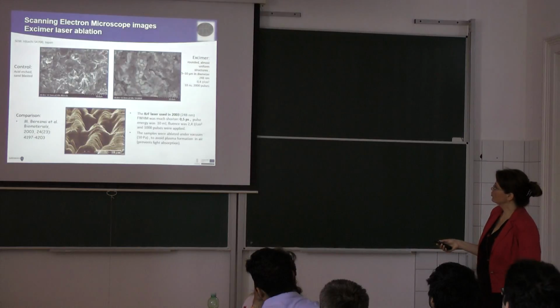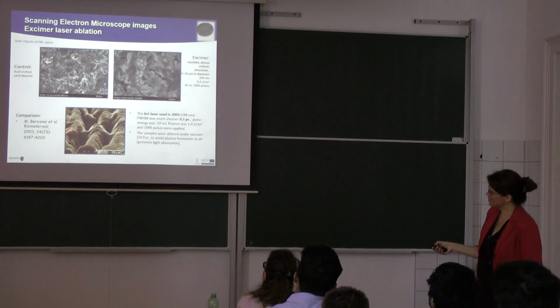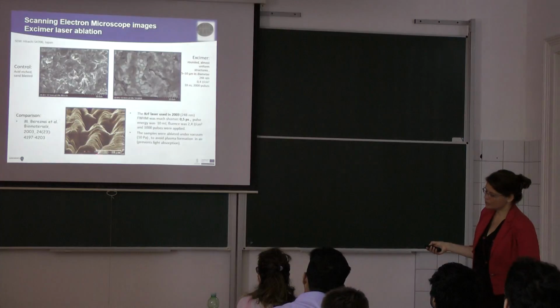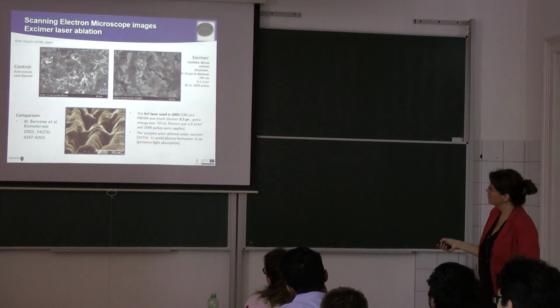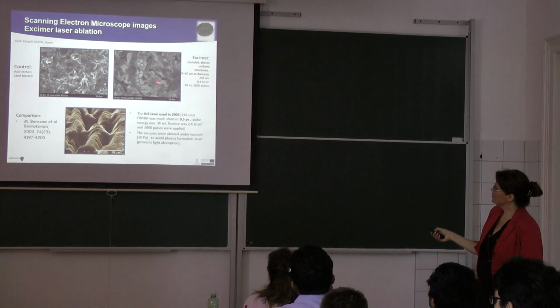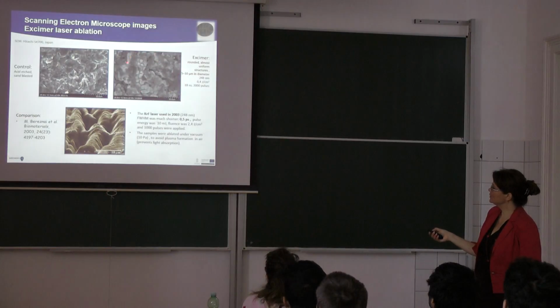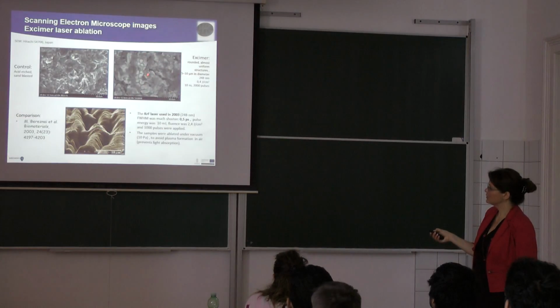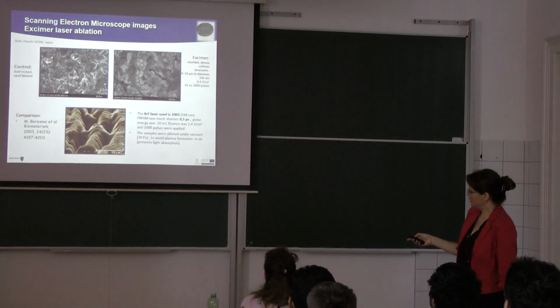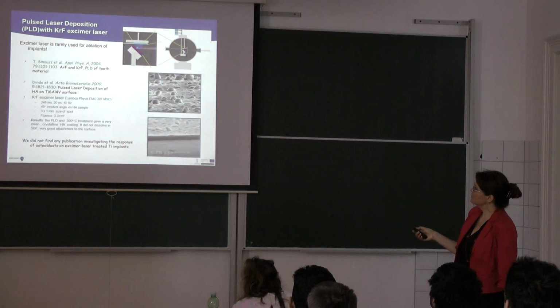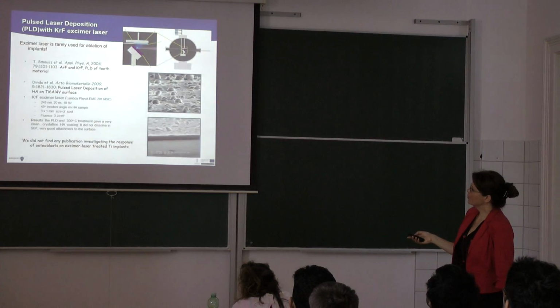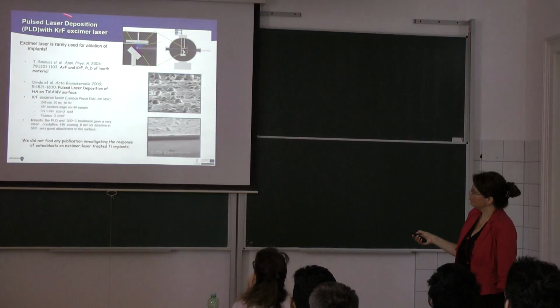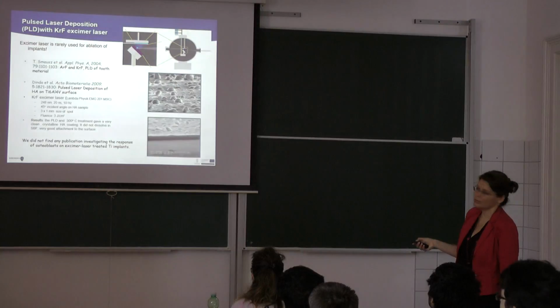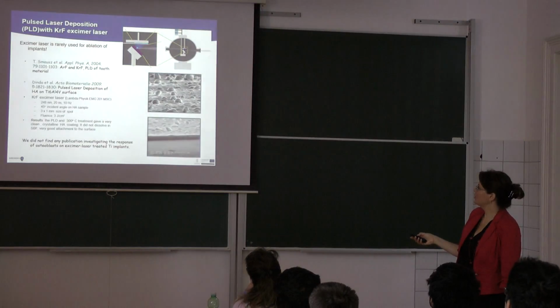Then if I want to show you the excimer laser treatment, so this was the old one. We wanted to reproduce this surface, but it was not possible. So our new excimer laser treated surface was looking like that, and it is not the same as we wanted. But okay, we were going further. This is, by the way, pulsed laser deposition. I just wanted to show you that krypton fluoride excimer laser treatment is used more for pulsed laser deposition, and we also had cooperation with the optics department working on that.